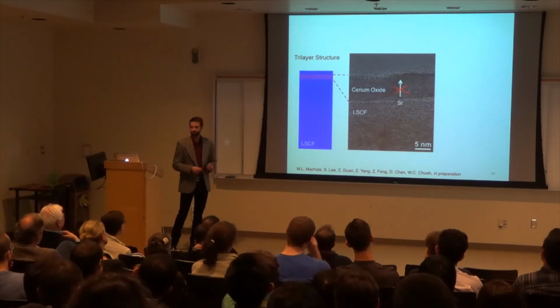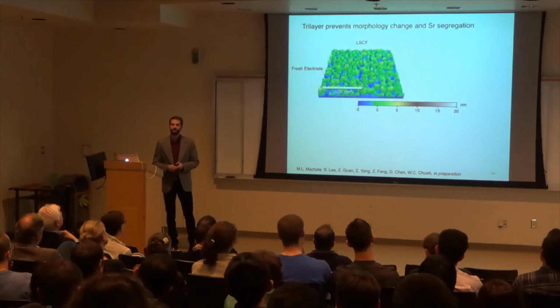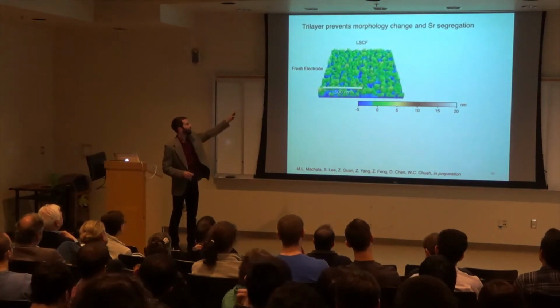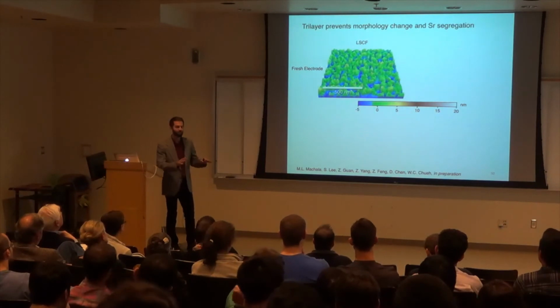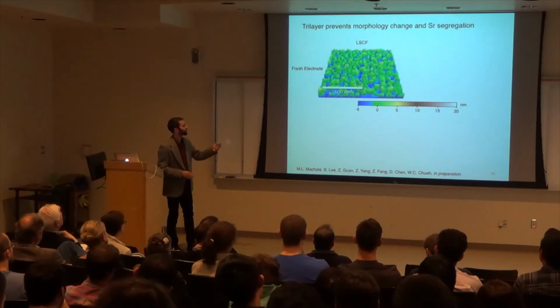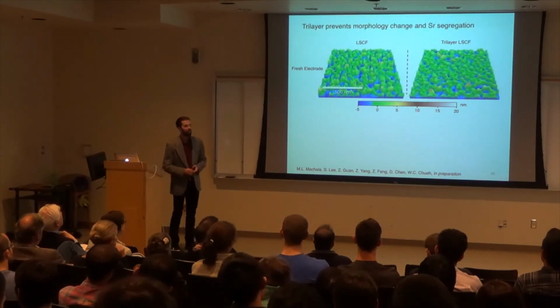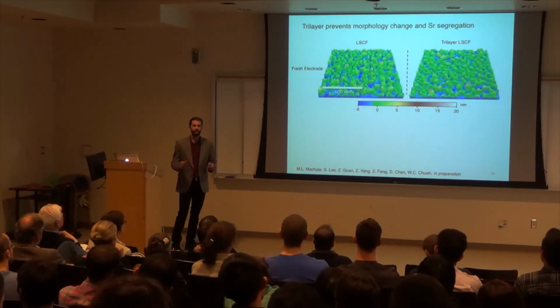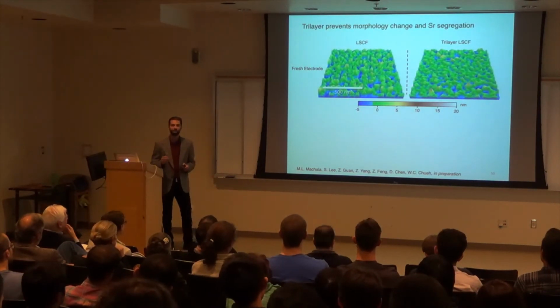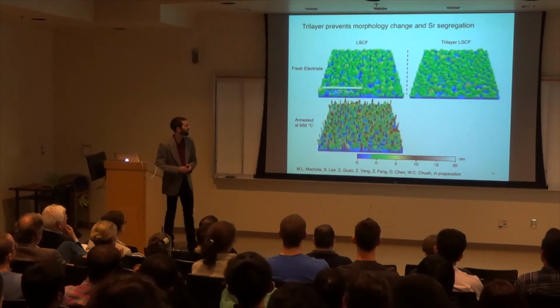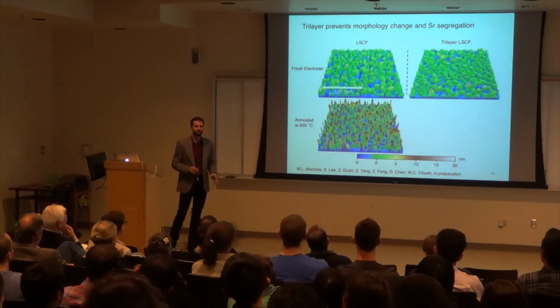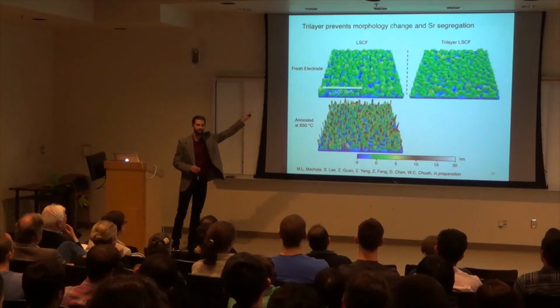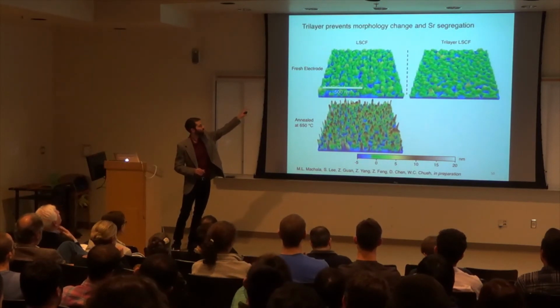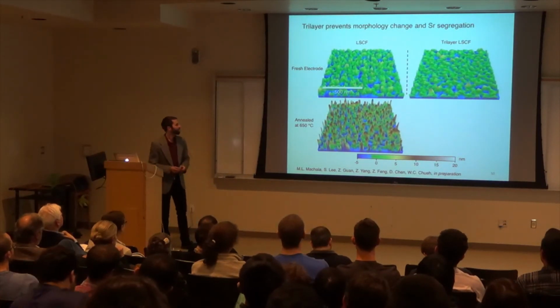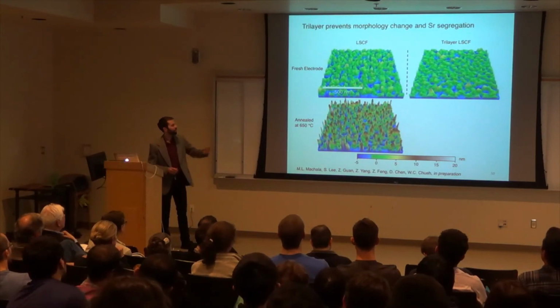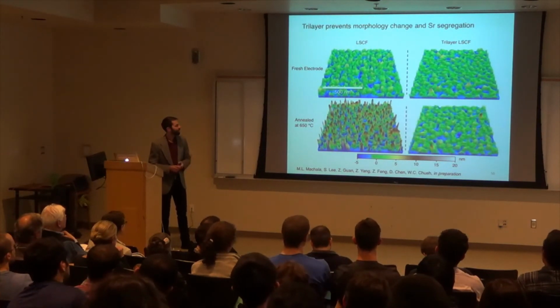And so to do that, we essentially first look at the surface morphology. Here we have the LSCF as a fresh electrode, and then we turn to the trilayer structure. We look at the surface again. They're not too dissimilar. Now, when we put them under reaction conditions, we see that after annealing at 650 degrees Celsius, the surface changes pretty significantly from the fresh sample to the annealed sample. But when we turn to the trilayer structure, we see that the surface doesn't change much.